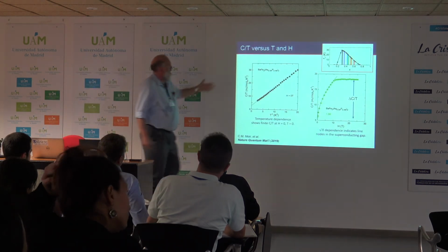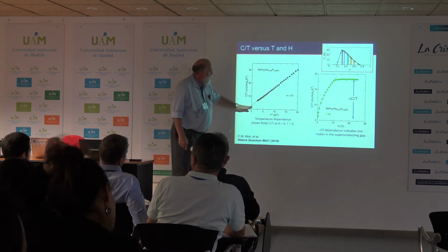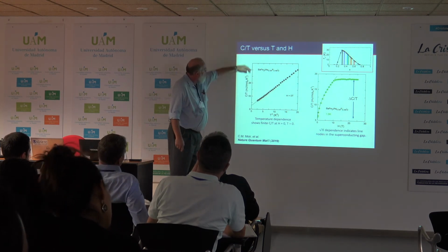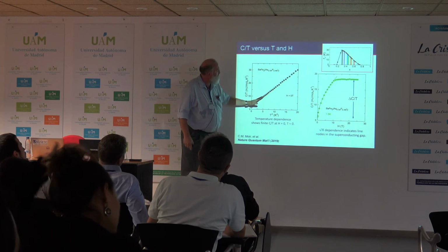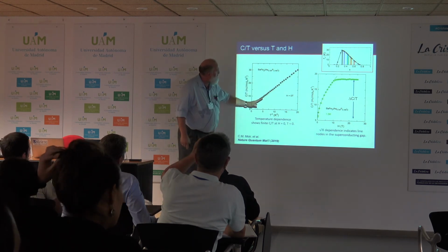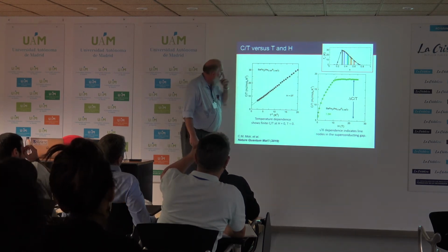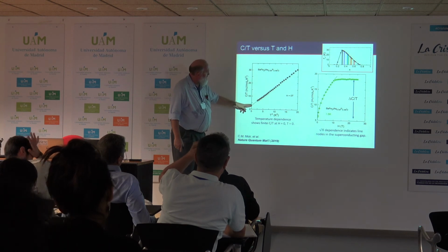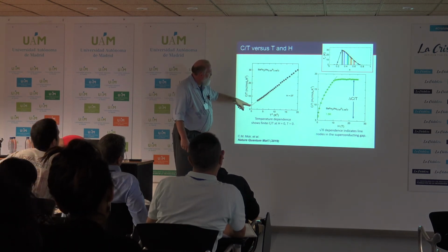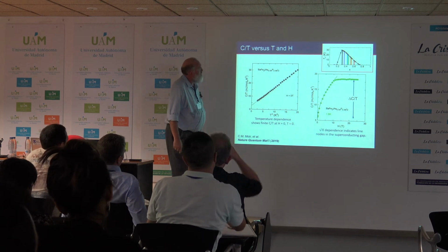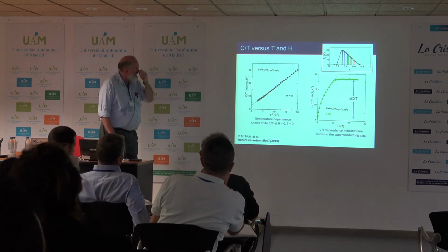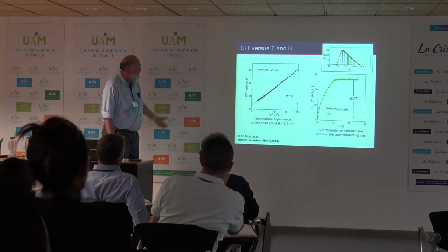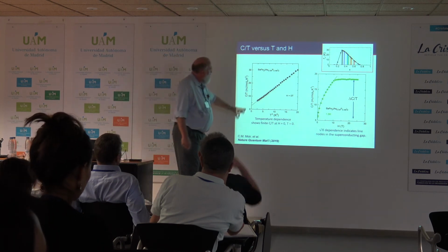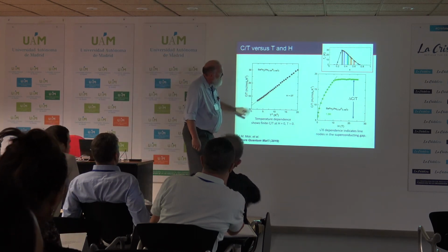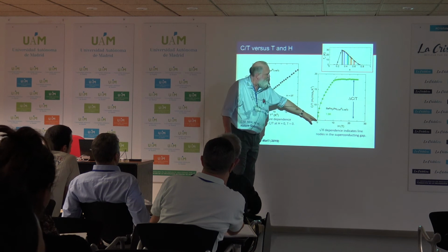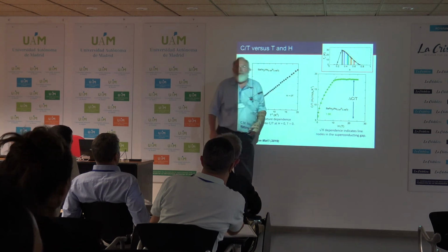So as a function of temperature, we get the canonical behavior, this linear plot of C over T versus T squared. This would be the phonon term that gives you this finite slope. You can back extrapolate to 0 temperature. This gives you the Sommerfeld coefficient, which gives you information about either disorder in your system or mass of your carriers. But the point is that we don't worry about this offset because we're really interested in what is recovered as you apply the magnetic field.